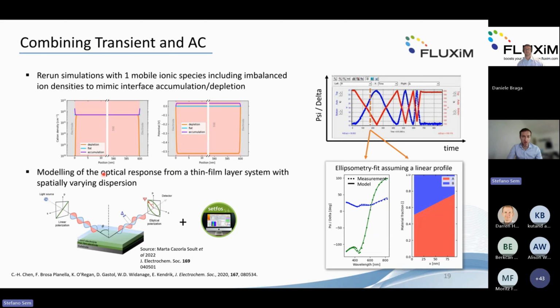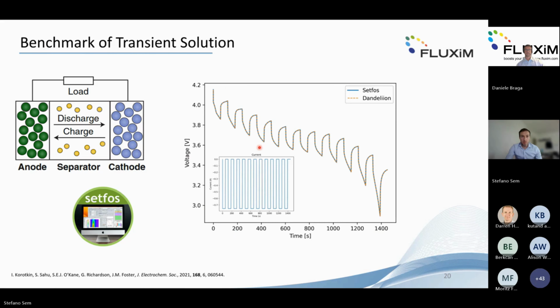Here is another result that we reached. From the optical module of Setfos, we were able to fit ellipsometry data. Basically, ellipsometry was done in operando during charge and discharge. And then we fitted this ellipsometry data with Setfos, so we were able to define the two species here, which will be the charge or discharge electrode. And you see that at some point, depending on the thickness, you have a different percentage of the charge or the discharge.